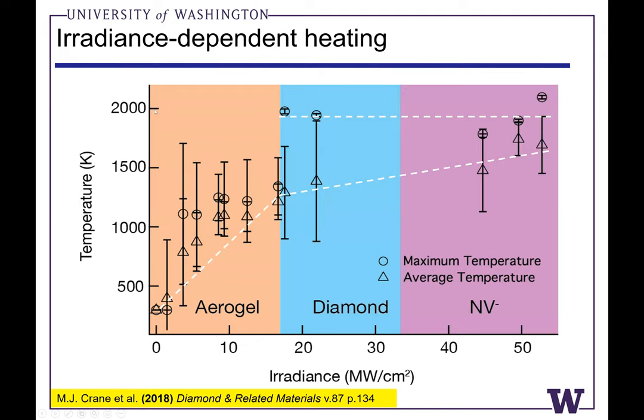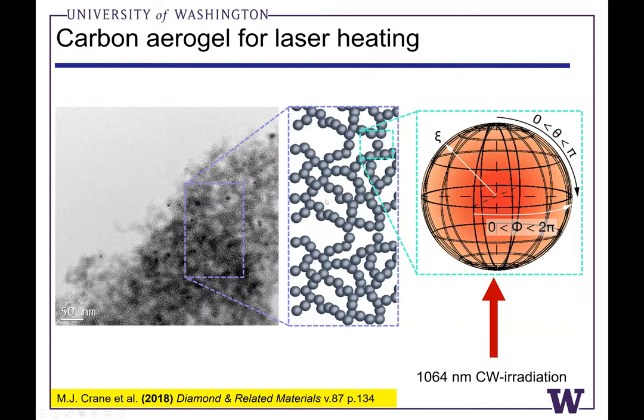that the temperatures can reach on the order of 2000 Kelvin. So we started to hypothesize, maybe we're melting the face-centered cubic argon pressure medium, and the fluid argon atoms can diffuse into the diamonds and get trapped in there in real time. So this is another cartoon of the amorphous carbon aerogel.